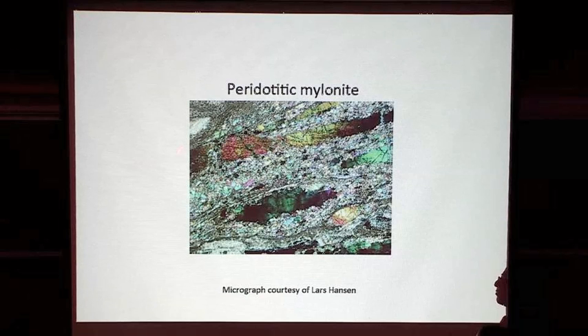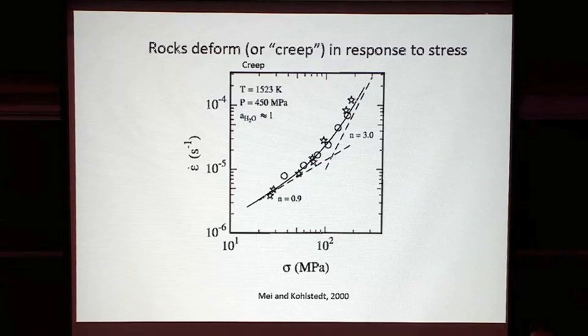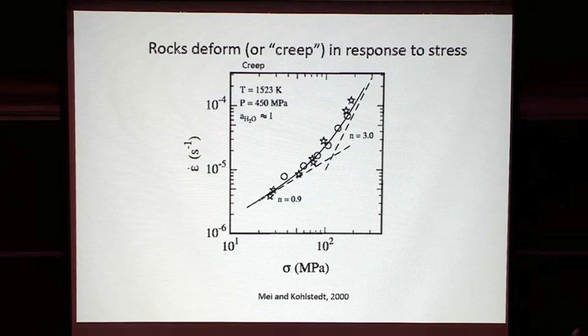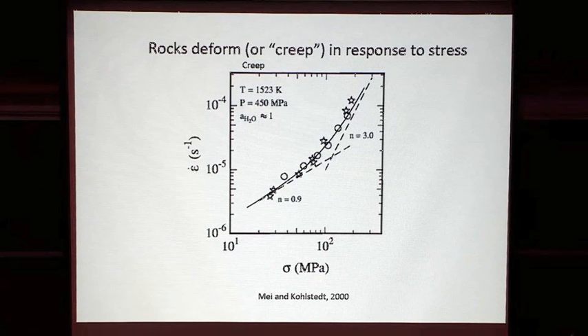And yeah, I'm almost done. So I just want to talk a little bit about deformation and creep in the mantle. There are different modes of creep that depend on things like the stresses and the grain size and so forth. This is a plot of olivine deformed at modest pressures in the presence of water. So this is really the weak stuff, as it were. The relationship between stress and strain: at low stress, there's this linear relationship, and that is thought to be diffusion creep, and I'll show you what diffusion creep is in a moment. And then at higher stresses, there's a change in the law. You get much, much higher strains for a given increase in stress, and this is thought to be dislocation creep.